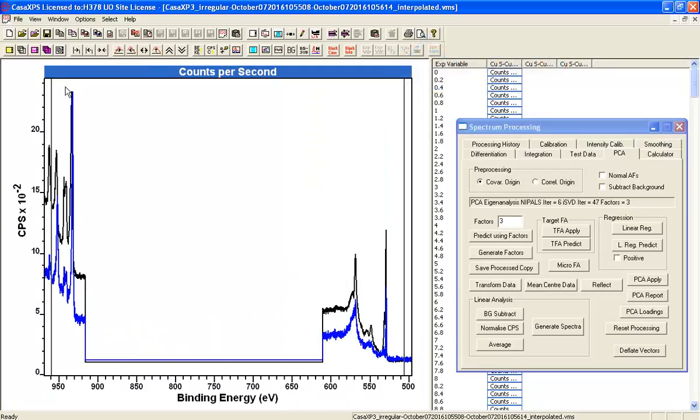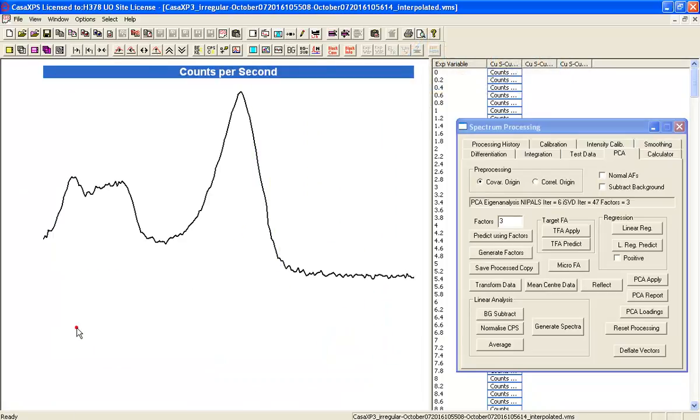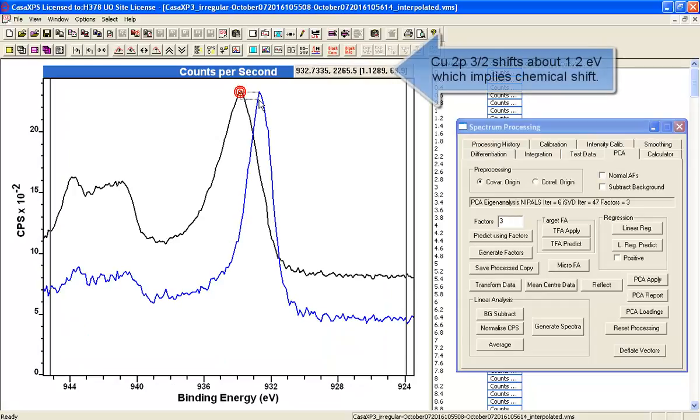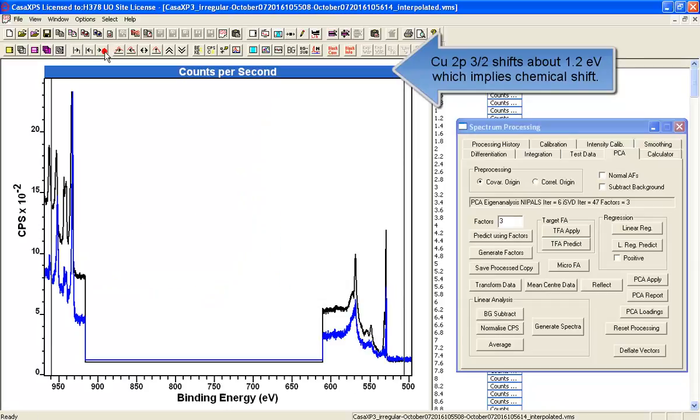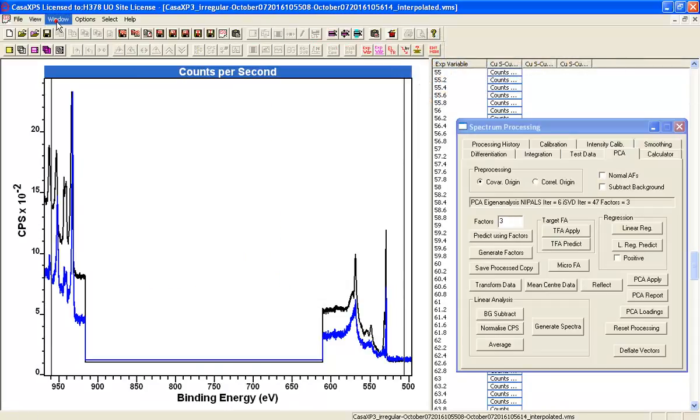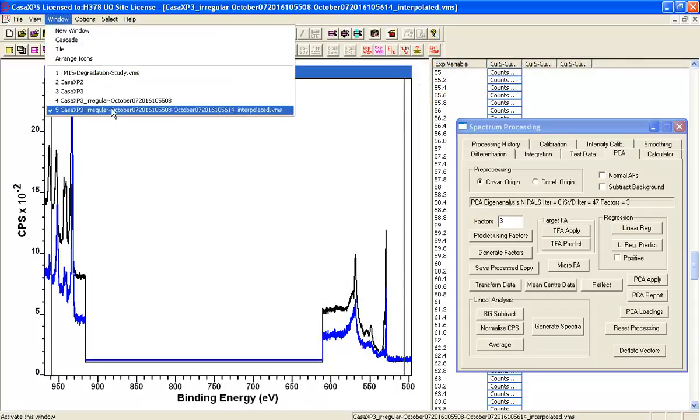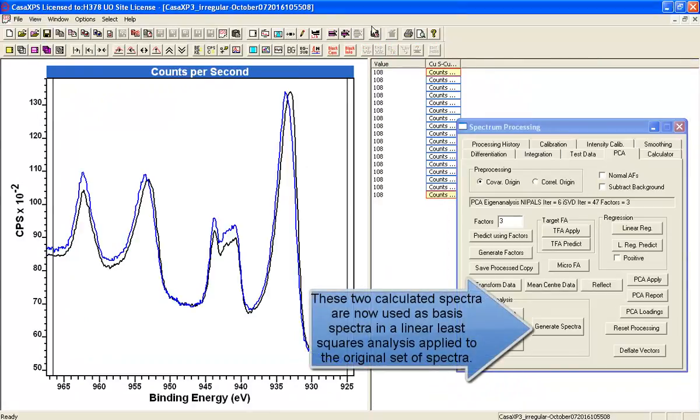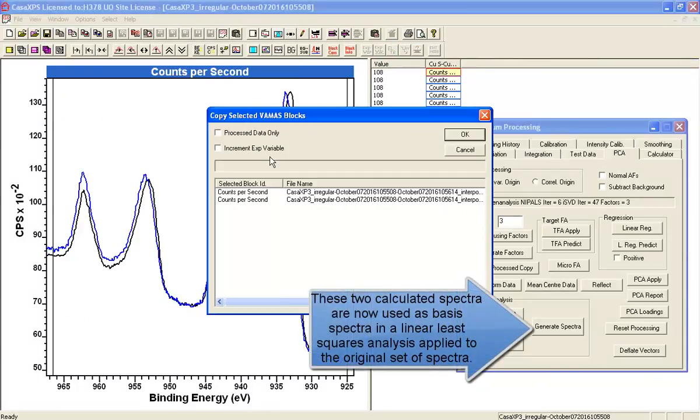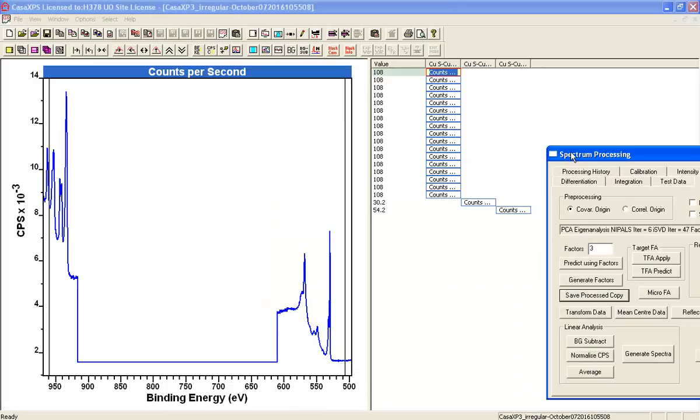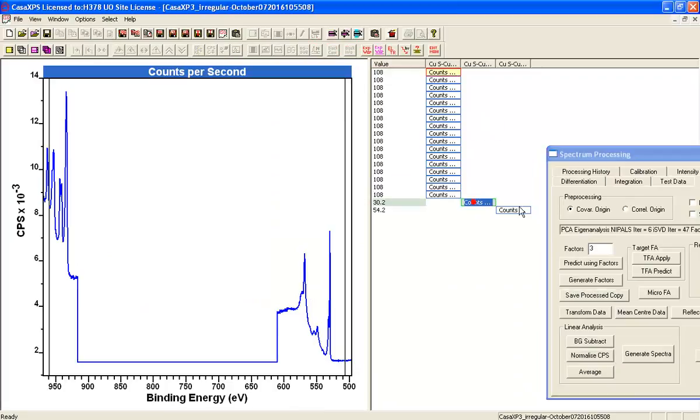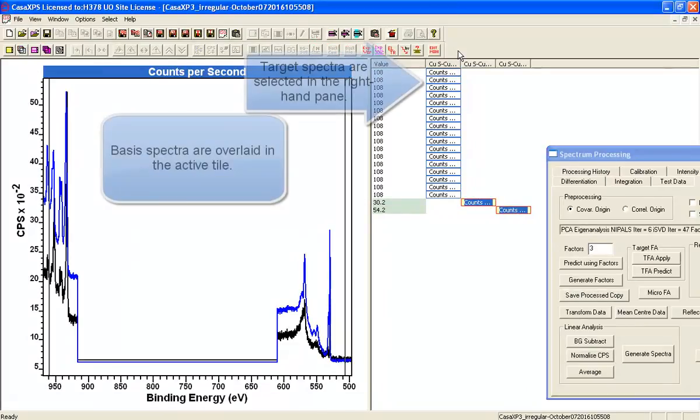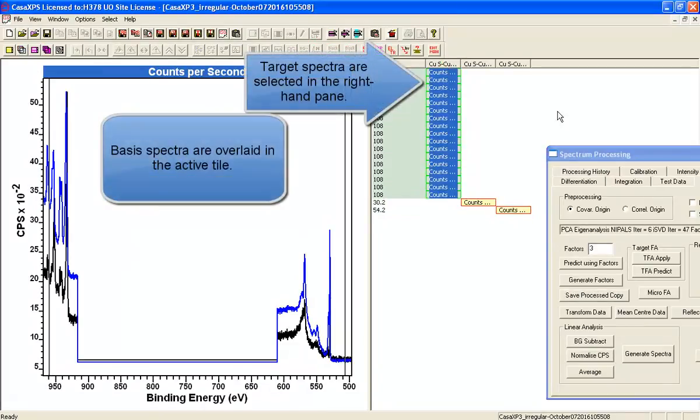And if we look at the Copper 2P, you can see there's a shift of about 1.2 eV rather. And so these are significant shifts in the Copper 2P and much bigger than the Oxygen 1S. So this suggests that we really do have line shapes that are giving us some further information about the oxidation state of these materials.